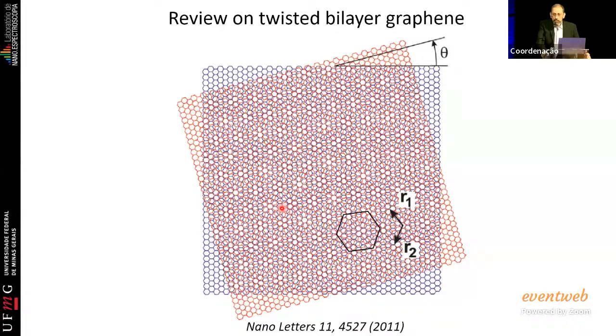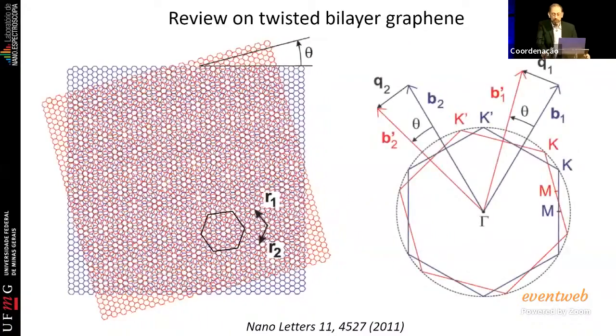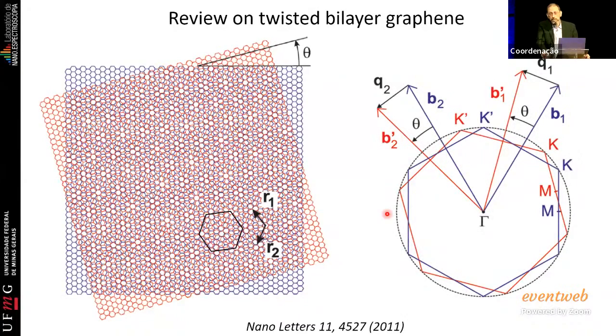So basically, when you have one layer rotated with respect to the other, as shown here by angle theta, you will have, as I already showed, a superstructure that is given by these two lattice vectors. And consequently, if you take the Fourier transform of the real space and go to the reciprocal space, the space of the waves, you also change the reciprocal space of the two lattices to a hexagonal reciprocal space given by these two arrows here.